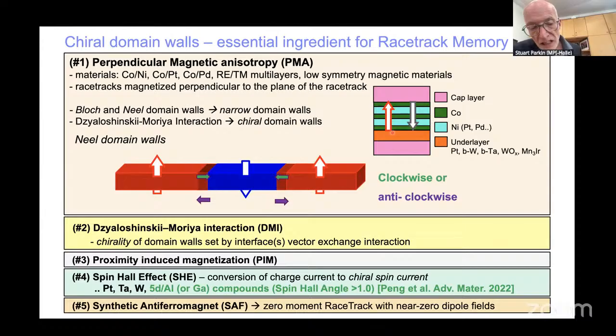And then finally, the basic ingredient for a racetrack, which is critically important, you need a racetrack with zero net magnetization, so you get near zero dipole fields. And we call this a synthetic antiferromagnet. This is the most important ingredient for racetrack. In fact, all of these ingredients are super important. Together, the anisotropy, the chiral interaction through the Dzyaloshinskii-Moriya interaction, the proximity-induced magnetization, the spin Hall effect, and the synthetic antiferromagnet create racetracks that have extremely interesting properties, where the domain walls can be moved at speeds exceeding 1 kilometer per second at current densities that don't significantly heat the racetrack. This is what makes it super important.